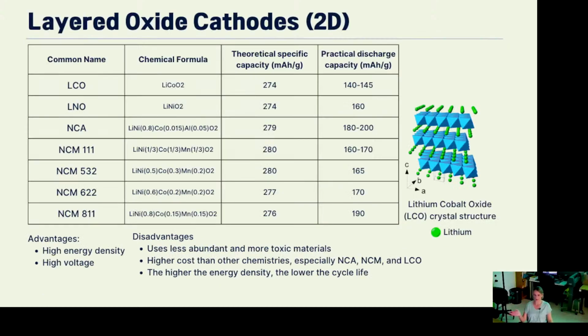Getting into 2D cathodes, layered oxide cathodes, these are your nickel-based cathode materials. So you have NCM, NCA, and the numbers next to the NCM, so this is nickel, cobalt, manganese, correspond to the ratio between the three materials. So 111 is equal parts nickel, cobalt, manganese, but 532 is 50% nickel, 30% cobalt, 20% manganese. And the higher nickel content you go, the more energy dense a material you get.